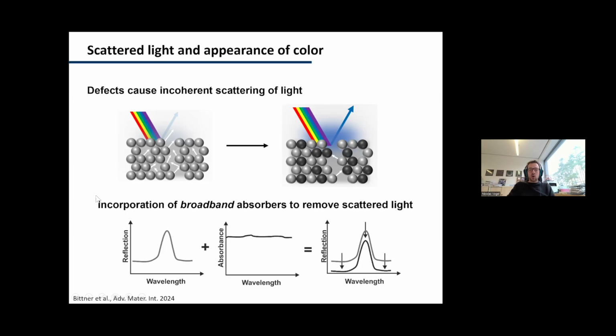So why does this work, or how does this work? We have a certain reflection peak from the photonic stop band. This is what we actually want to observe. But because of this incoherent scattering, we also create a reflected light throughout the visible range. And this gives a whitish overall hue to this entire color pigment. And now if we add something that absorbs, typically broadband, so takes out all the light, and we combine this, then we can reduce the overall reflection of light.